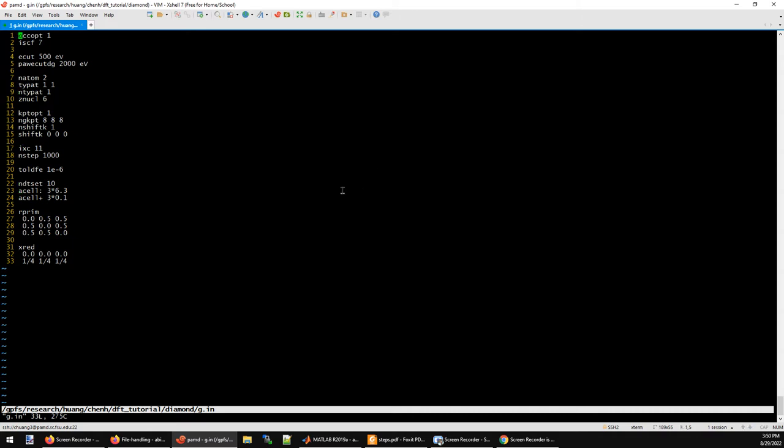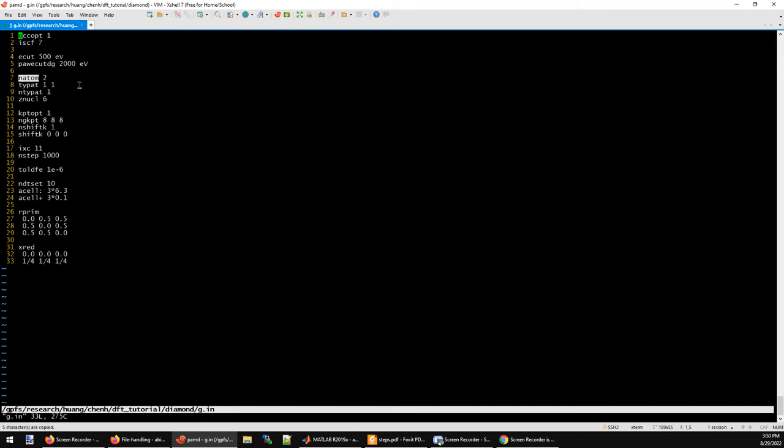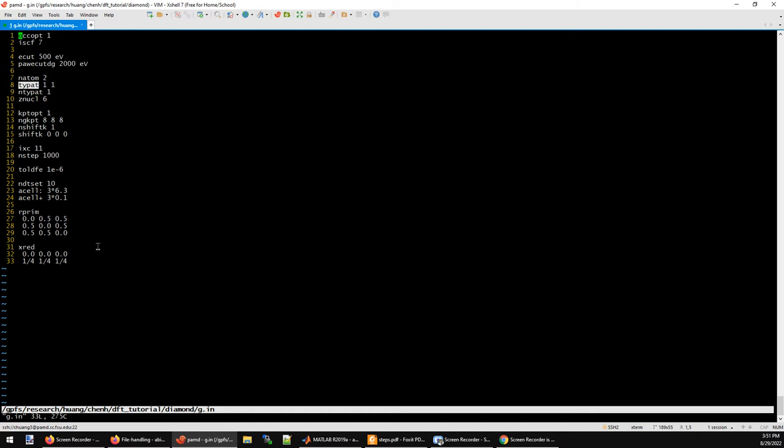This is the pre-made input file for my simulation. I'm going to perform the PAW calculation, so you can see that I have an extra keyword to define a fine mesh for the PAW simulations. This is the ECUT for the soft part of the orbitals. The number of atoms is 2. I have only one carbon element in this material, so the nuclear charge is 6. The number of type of atoms is 1, and the type of atom is 1 1 because I'm going to have 2 atoms in this simulation cell.